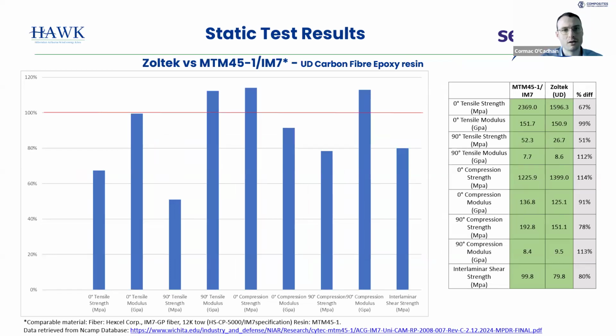And this is the Zoltek. So this is the UD compared with a UD from the NCAMP database. We see our 100% baseline here for the baseline material. So our 0 degree tensile strength is a good bit lower, 67%, and our 90 degrees. So that's, you'd look to improve on that really. I suppose one of the main things you look at is your 0 degree compression strength. So that is higher. So we're seeing 114%. So that's a good sign, and that's what you'd be expecting with the pultruded process. Really good fiber alignment and good material properties.